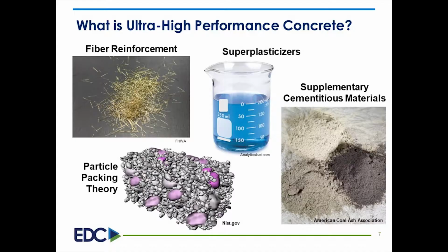In addition to Portland cement, fine aggregate, and water, ultra-high performance concrete also has a large amount of steel fibers. So we use reinforcing steel in conventional concrete to carry tension and control cracks, and the steel fibers are used to do this in ultra-high performance concrete. I said there's a lot of steel fibers. I'll say it again. There's a lot of steel fibers. It's 2% by volume. It's about 250 pounds of fiber per cubic yard.